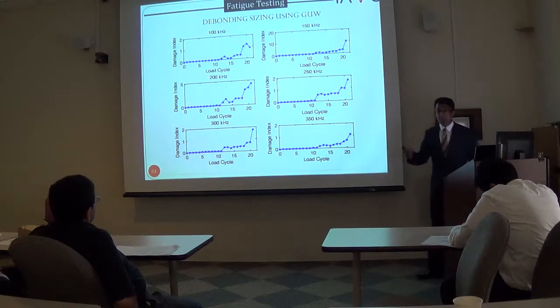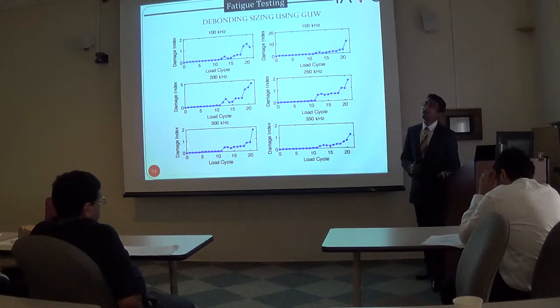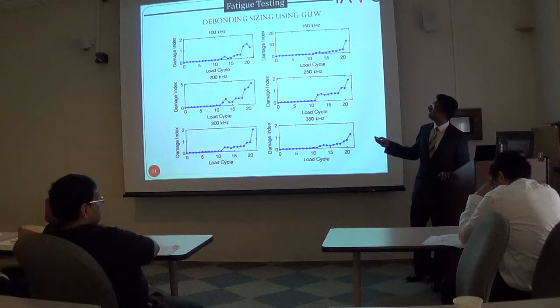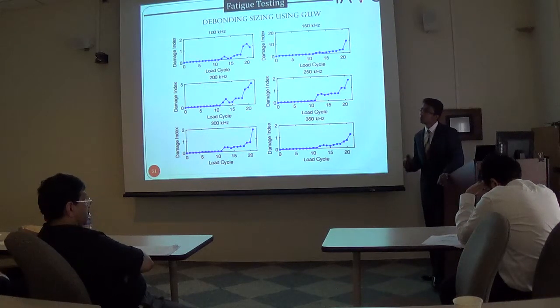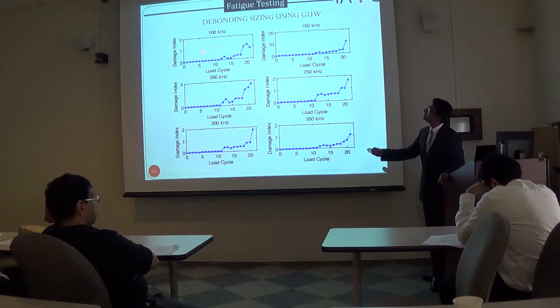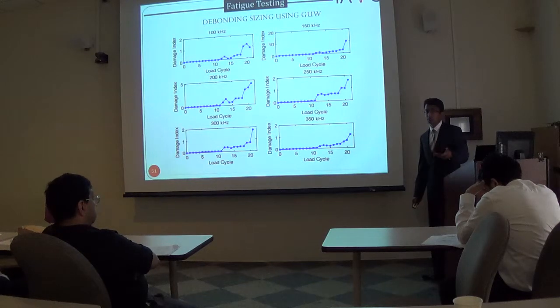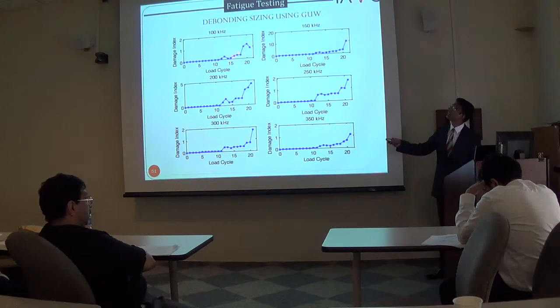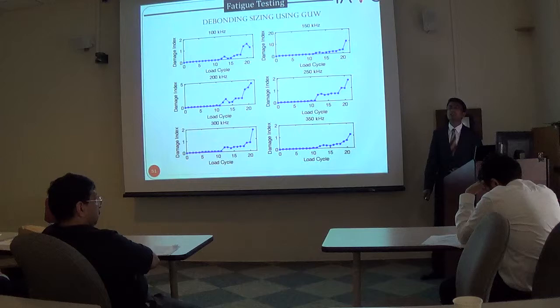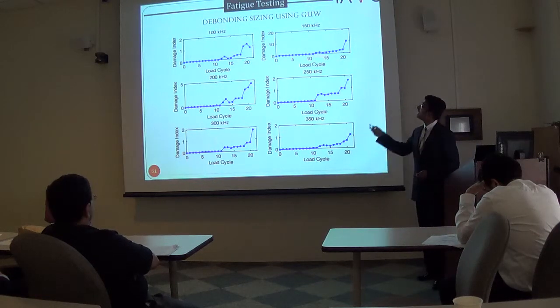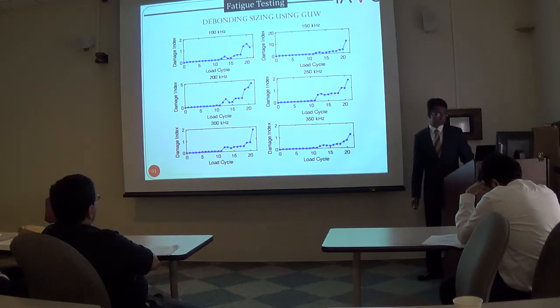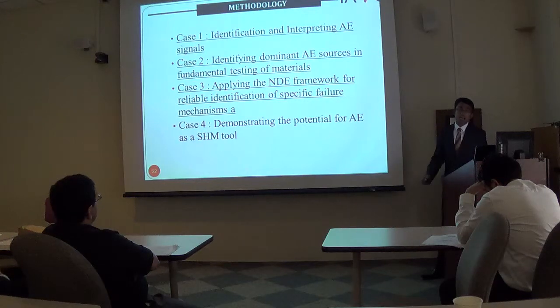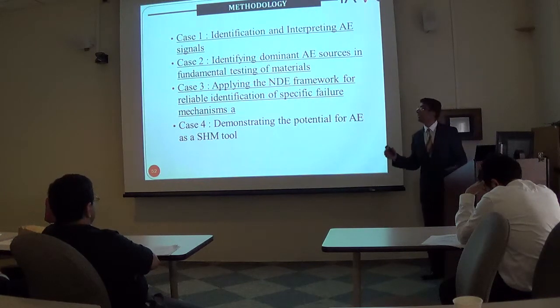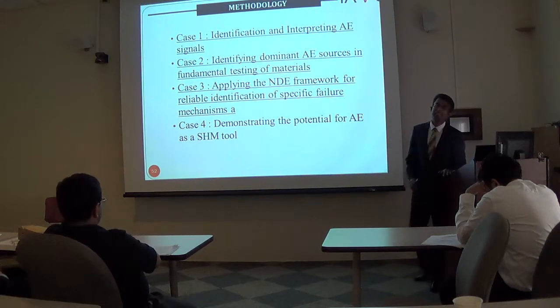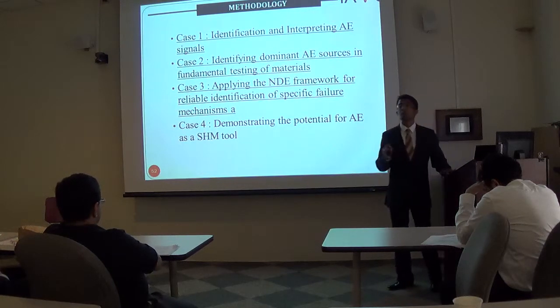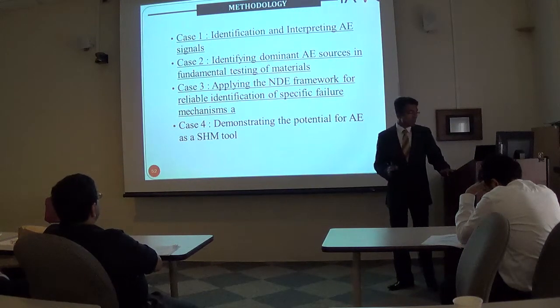So in order to indeed validate the onset of debonding and interpret the AE signals, guided ultrasonic waves were also generated to confirm the debonding of the material. And it can be seen exactly after the 11th load cycle, which is when we saw the visual debonding, that the damage index developed using guided ultrasonic features was seen to increase at the different frequencies as noted here. So the last goal was to apply acoustic emission testing as a potential structural health monitoring tool for real-time damage detection.